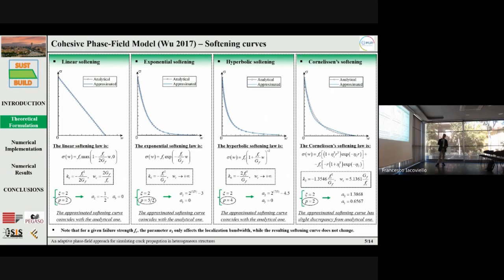This slide compares linear, exponential, hyperbolic, and Cornelissen softening curves obtained by the model with the analytical ones. For each type of softening curve, we have reported the analytical law and the expressions of K0 and WC, which represent the initial slope and the ultimate crack opening displacement, respectively. In the slide appears the exponent t, which appears in the function W, which assumes this value in order to obtain the correct value of WC. The approximated curve obtained by the model coincides with the analytical one for linear, exponential, and hyperbolic softening, but shows a slight discrepancy from the analytical one for Cornelissen.